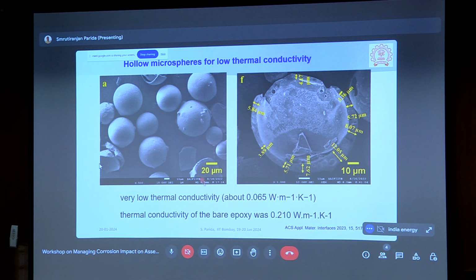The beauty of this system is that it has a very low thermal conductivity, 0.065 watt per meter per kelvin. If we add this into resins such as epoxy, it further reduces the thermal conductivity of the total coating. But the problem with this kind of material is that it is very difficult to disperse unless we do some surface modification. That is what we incorporated in this material so that it is easily dispersed in a coating.